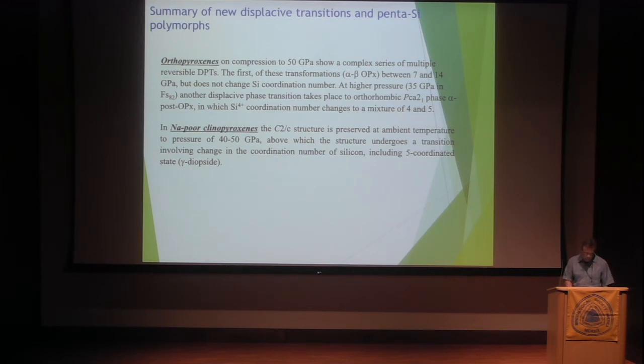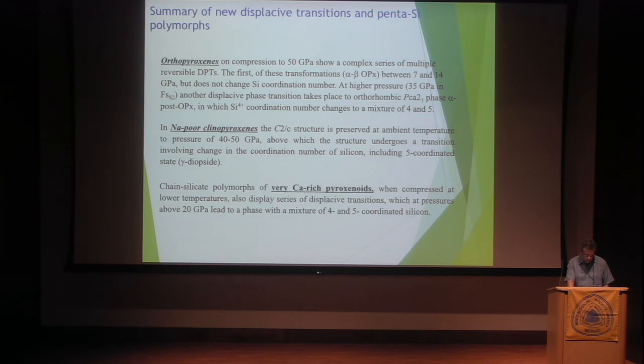In sodium-poor clinopyroxenes, these phases start with a C2/c symmetry at ambient conditions. This symmetry is preserved at ambient temperature to pressure of about 40 to 50 gigapascals, above which the structure undergoes a transition involving changing the coordination number of silicon, including 5-coordinated states, like the one that we observed in diopside.